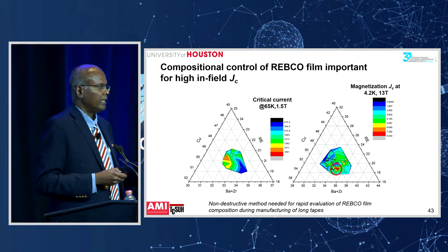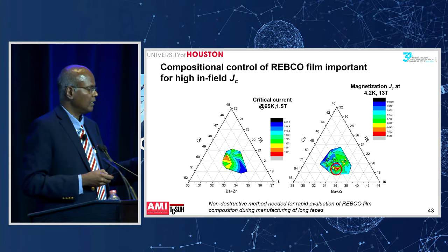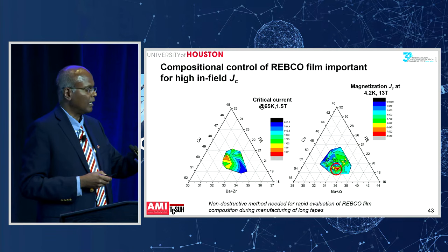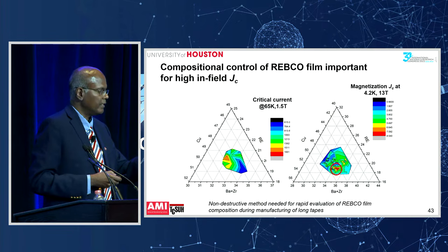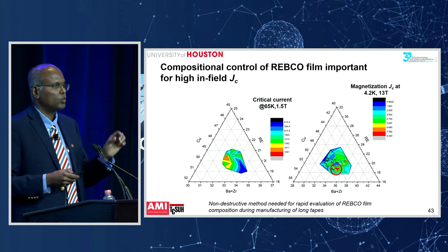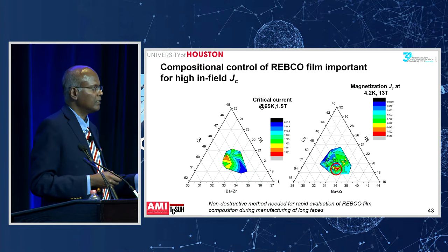It's quite challenging though. The reason for that is this compositional map I'm showing right here. You have the rare earth, the copper, the barium and the zirconium, and what you see on the color chart is the current carrying capacity at 13 Tesla. The red part of the chart is very small, right? So what it means is that you need to control the composition of the film within 1 atomic percent. The barium, copper, rare earth and zirconium have to be controlled within 1 atomic percent in order to get the peak performance.